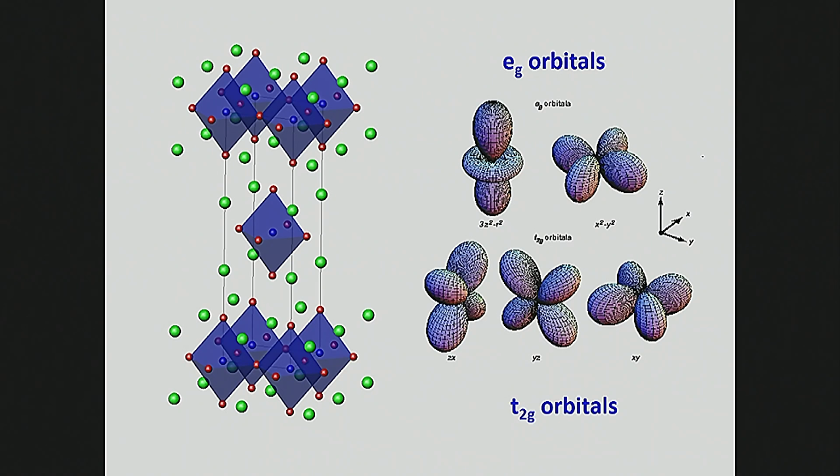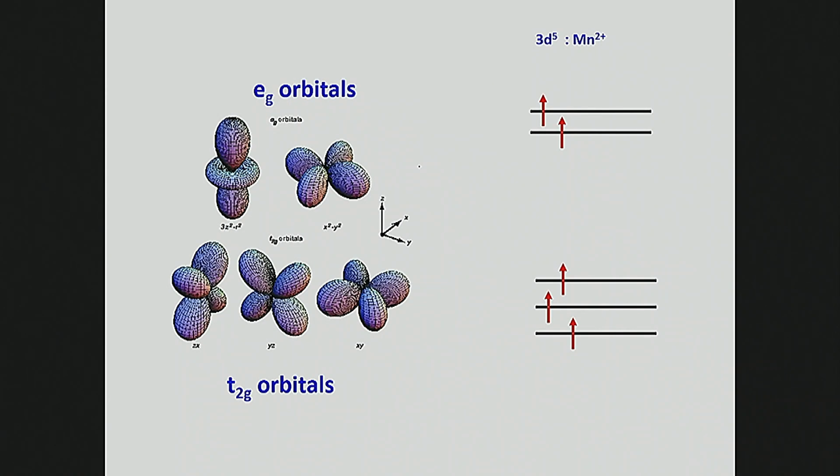So that's a relatively high energy state, because the electrons, which are electronegative, point at the oxygens, which are also electronegative. These are lower energy states because the electrons point away from the oxygen 2- ions. That's all there is to it. But we've got these 10 states. It's really 5 orbitals, into which we can put 2 different spins. And that's how we're going to generate our magnetic moments.